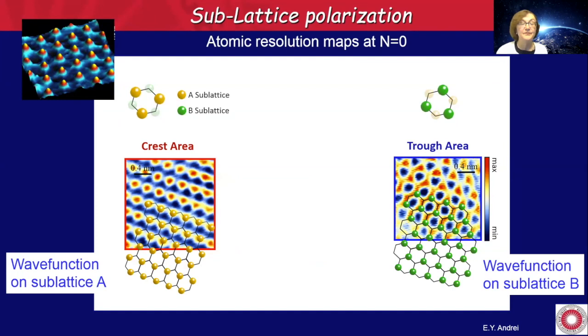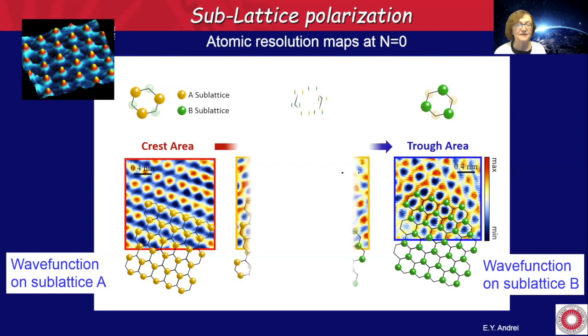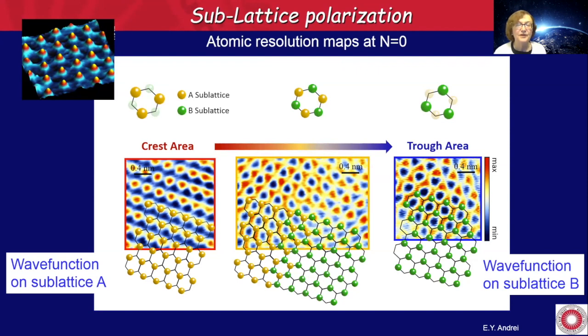If we do spectroscopy of this layer, and we go to the crest and look at the density of states maps, you see that this is a triangular structure rather than a hexagonal, honeycomb structure. So we only see the atoms in one sublattice. And then when you go to the troughs, you see the atoms in the other sublattice. That tells us that what we have here is a pseudomagnetic field that is induced by the strain, which is present in this buckled structure because of the stress of compression. In the crossover region in between the two, the wave function sits on both sublattices. So we know that we have a strain-induced pseudomagnetic field here.